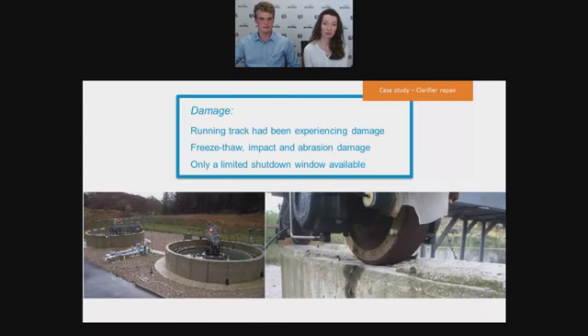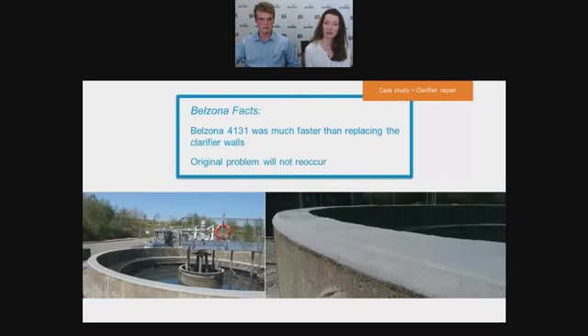At this water treatment plant in Scotland, 2 clarifiers were in need of repairs. The running track on top of the wall had been experiencing impact and abrasion damage due to the arm, and the substrate was seriously damaged. However, there was only a limited shutdown window to make any repairs. The chosen material was Belzona 4131.